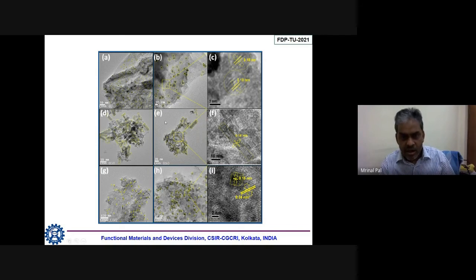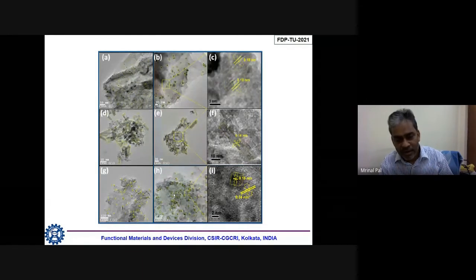That's why this rod kind of structure has formed, and this is the high resolution structure which shows the splitting of this lattice fringes. This one is a nanocubic structure. This is also just by controlling the preparation process and parameters, nothing else. So all of them are graphene cobalt nanocomposite, where cobalt has different morphology. Graphene is the same, the background is graphene, as you can understand.